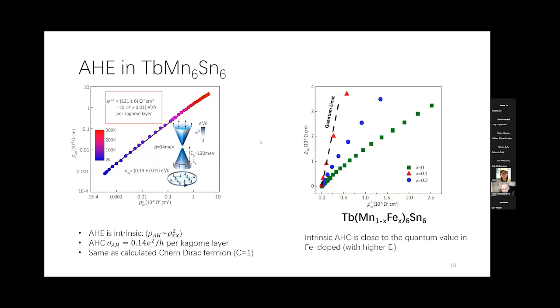So besides this spectral measurement, we can also detect massive Dirac fermions from the transport measurement. This plot is a scaling relation of the Hall resistance with longitudinal resistance. You see a very clear intrinsic anomalous Hall effect, and the anomalous Hall conductivity equals 0.14 e squared over h per kagome layer. This is exactly the same as the calculated Berry curvature for a Chern-gapped Dirac fermion. Also, we can do some electron doping on this compound, and you see a strongly enhanced intrinsic anomalous Hall conductivity, which is consistent with